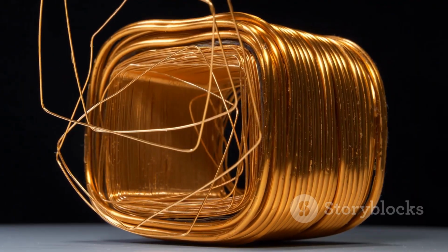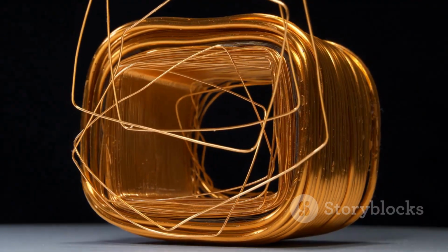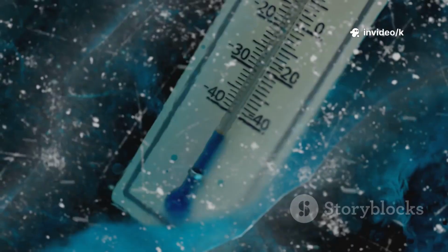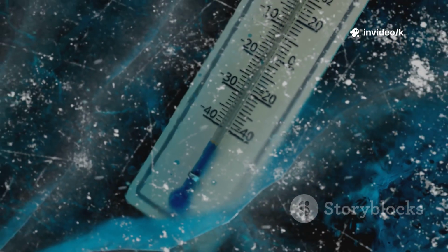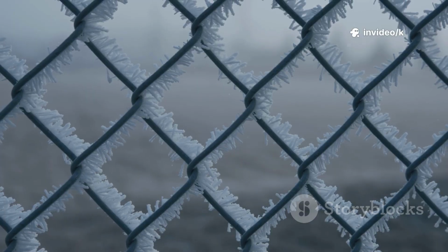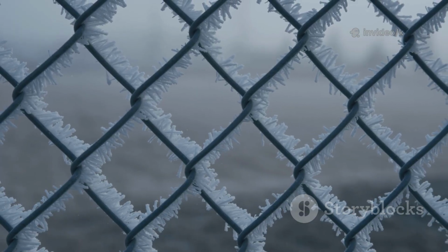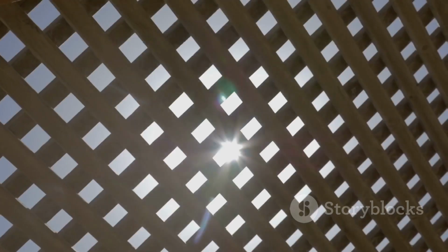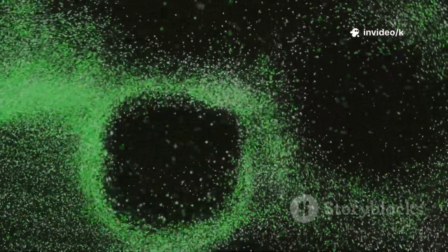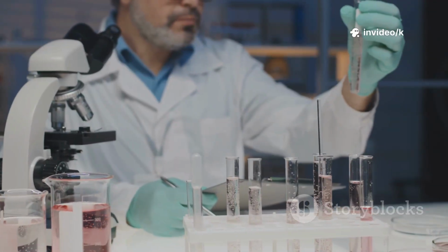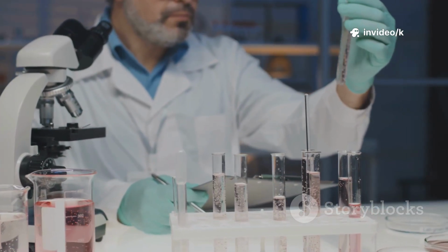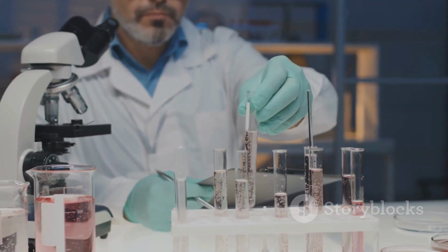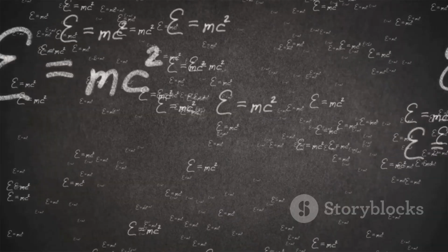Why is this so useful? Imagine you want to know how pure a sample of copper is. You can measure its resistance at a very, very low temperature. At temperatures near absolute zero, the lattice vibrations almost completely stop. The traffic jam part of the resistance goes away. Any resistance that's left must be due to the permanent red lights, the impurities. So, by cooling the metal down, Matthiessen's rule lets us separate the two effects and get a direct measure of the material's purity. It's a clever trick that works surprisingly well in many situations.